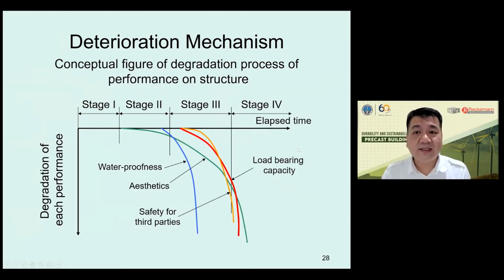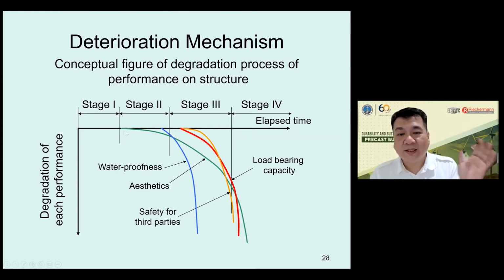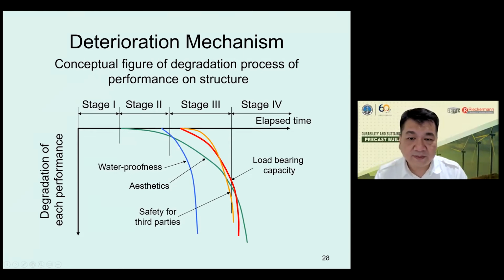And then, this is the degradation process. Normally we divide the degradation process of the building into 4 stages. Stage 1 is nothing, because we don't see what happened in the concrete. Normally the salt water enters the concrete building, or the carbonation front is moving. So stage 1, no degradation. Stage 2, when there is a static condition, cracks appear. So when there is corrosion and then crack, we call it stage 2. And then for the waterproofness, the crack will cause some problem.